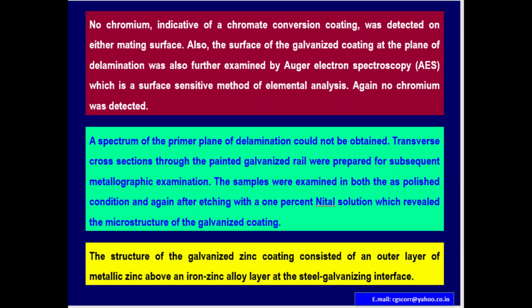Transverse cross sections through the painted galvanized rail were prepared for subsequent metallographic examination. The samples were examined in both the as polished condition and again after etching with a 1% nital solution, which revealed the microstructure of the galvanized coating. The structure of the galvanized zinc coating consists of an outer layer of metallic zinc above an iron zinc alloy layer at the steel galvanizing interface.